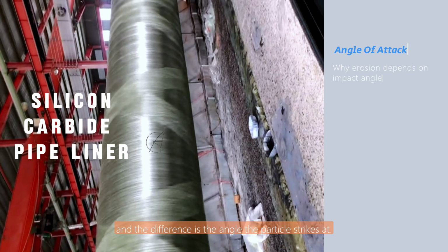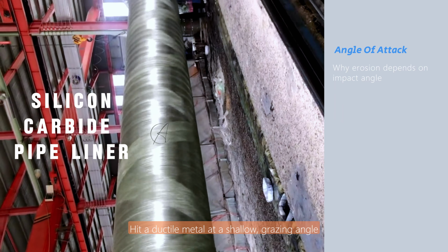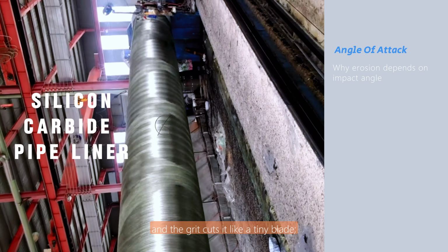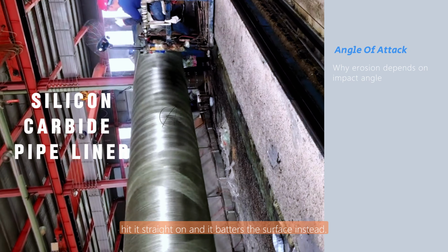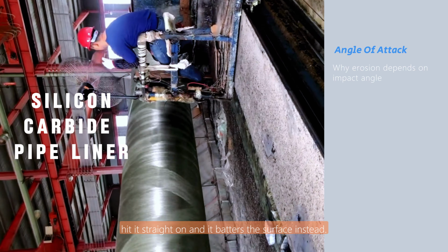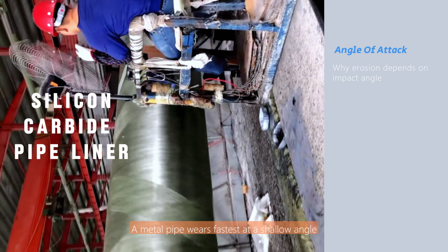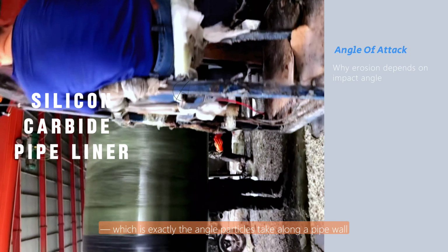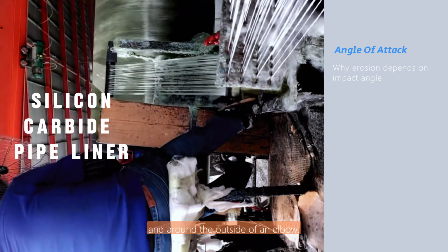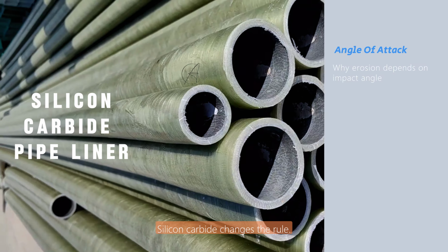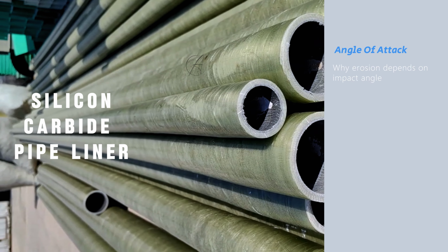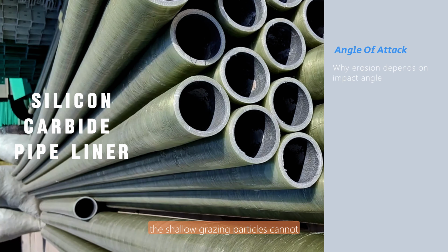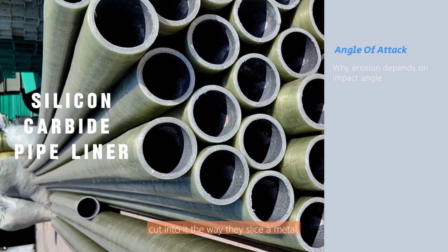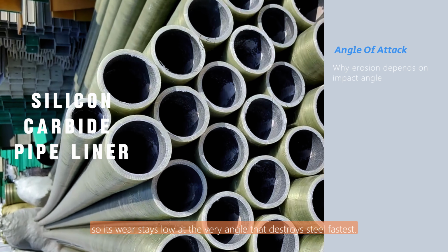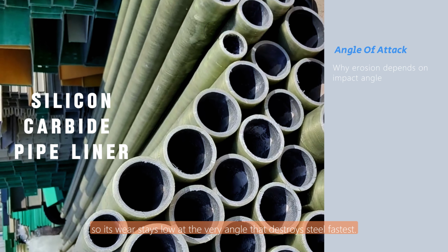Erosion is not one process but two, and the difference is the angle the particle strikes at. Hit a ductile metal at a shallow, grazing angle and the grit cuts it like a tiny blade. Hit it straight on and it batters the surface instead. A metal pipe wears fastest at a shallow angle, which is exactly the angle particles take along a pipe wall and around the outside of an elbow. Silicon carbide changes the rule. Because it is so hard, the shallow grazing particles cannot cut into it the way they slice a metal, so its wear stays low at the very angle that destroys steel fastest.